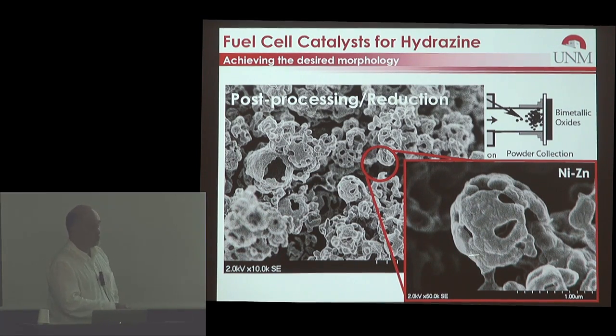So this catalyst actually looks like a, what? It looks like an electrolyzer catalyst. It doesn't look like a fuel cell catalyst, because when you're oxidizing hydrazine, you're evolving nitrogen like crazy. Bubbles taking up, okay? Similar to an electrolyzer. A fuel cell that works like an electrolyzer from the point of view of mass flow.